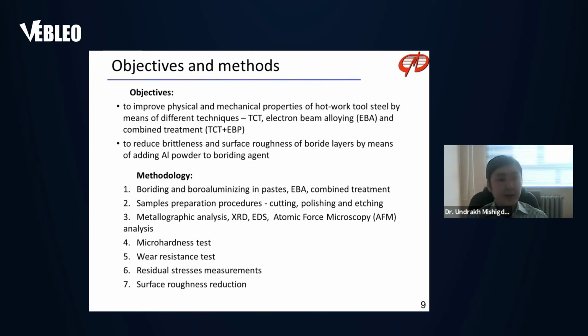Based on what has been said, the objectives of this research are to improve the physical and mechanical properties of hot work tool steel by means of different techniques such as TCT, electron beam alloying, and combined treatment, and to reduce brittleness and surface roughness of boride layers by adding aluminum powder to the boriding agent. After different surface engineering techniques, samples were subjected to common sample preparation procedures, and structure, composition, and different tests were conducted, including residual stress measurements and surface roughness reduction.